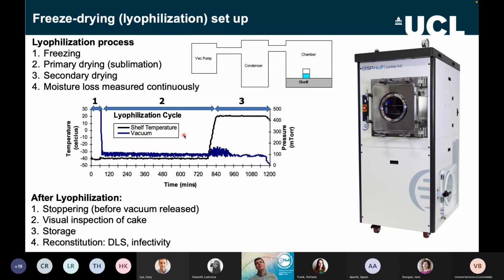For those who are less familiar with freeze drying, this is what it looks like. We have one of these, a Lyostar, sat in our pilot plant, and essentially you go through various stages. You freeze your material, you then apply a vacuum so that you can start drying or subliming the material for some period of time, and then you might increase the temperature to go into a secondary drying stage. And there are variants of this, and I'll discuss some as we go through. After that, you stopper, and then we inspect the cake, store it for a period of time, maybe at different temperatures, and then reconstitute and measure dynamic light scattering for particle size distribution and the infectivity, which is done in Oxford.